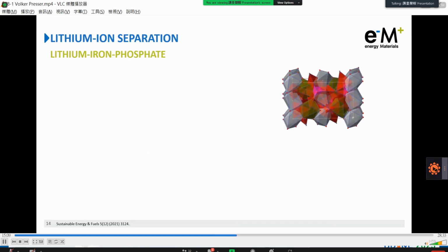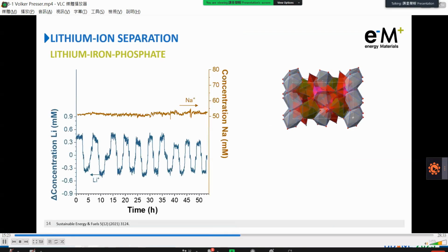The crystal structure of lithium iron phosphate, with the unique confined space for lithium, really favors lithium size- and charge-wise over other cations. In experiments, it's not surprising to have experimental data like the one that you see here, where we flow sodium and lithium containing solutions in a mixed system, but only detect the uptake and release of lithium during electrochemical cycling of lithium iron phosphate.